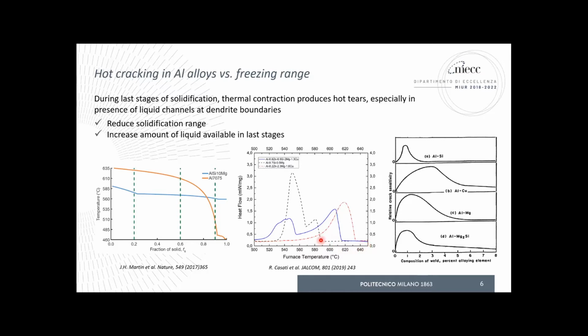While the black line is for an aluminum 7% silicon. Not exactly, but pretty much the same behavior as the blue line here. So we have primary solidification of alpha aluminum, and then at the end of solidification, another bump, another peak, very large, very wide as well, that corresponds to the eutectic aluminum silicon solidification. This is a good point because the large amount of liquid which is available in the very last stage of solidification can smooth down the curve, and can possibly also promote healing, backfilling of the cracks. So you end up having a very sound microstructure.